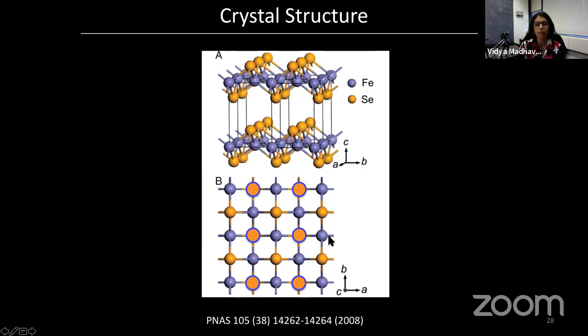So this is the top view. And these orange round circles represent the square lattice made by the top selenium atoms. Notice that you also have selenium atoms at the bottom, but they're slightly shifted. So these other orange atoms are the bottom selenium atoms. And this shift is going to be important when we look for propagating Majorana fermions in the system.